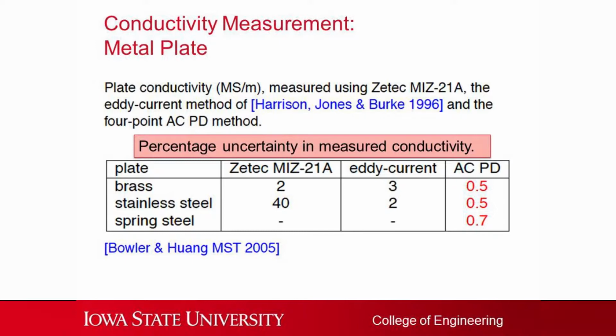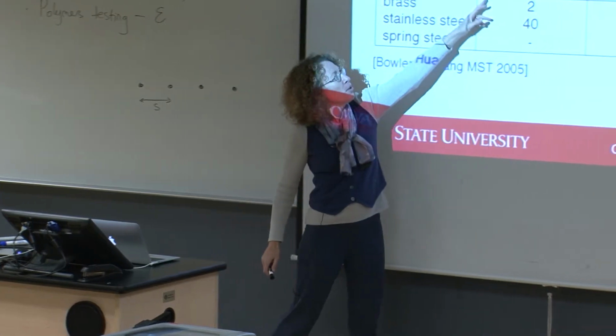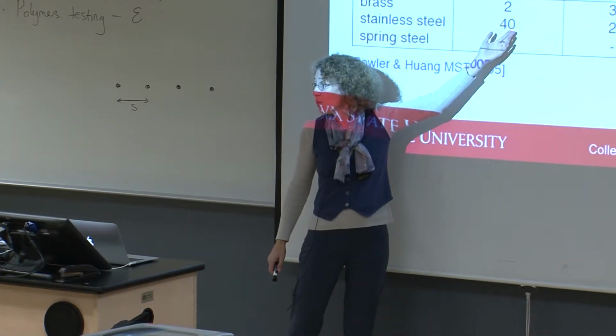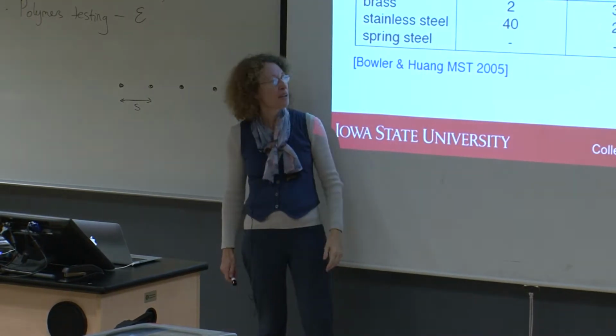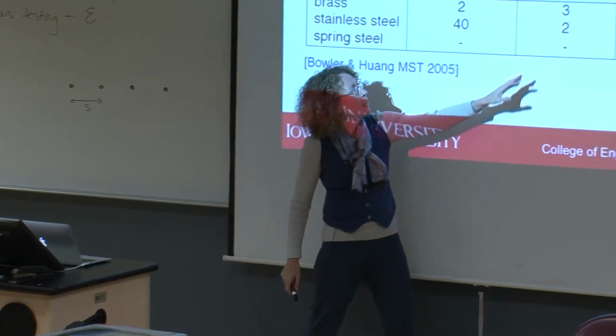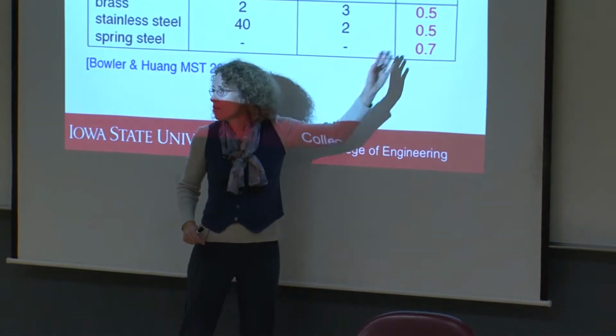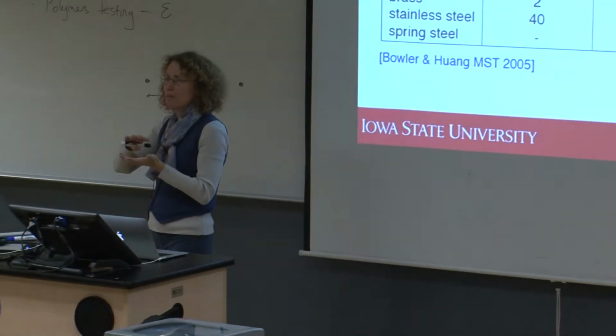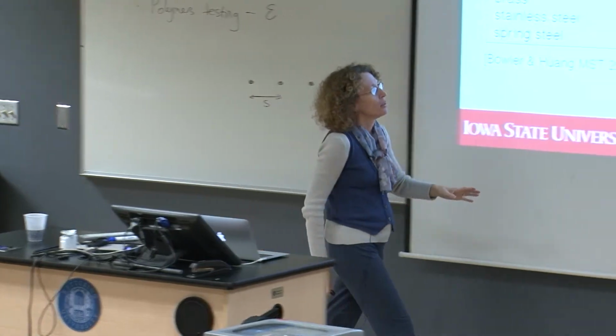I'm actually here in Michigan to go to a meeting about measurement science, and we care about how accurately we can measure things. So in this example, with our commercial instrument, when you get to measuring conductivity of a steel, it has really poor accuracy. It's about 40% wrong, okay? So we're not impressed with that one. 2% is all right. That's on a non-magnetic material. The eddy current system we have in our lab does fine. But then if you really want to get down to understanding the difference between some different alloys that have similar composition, it's good to have as much accuracy as you can, and our system did well with that.